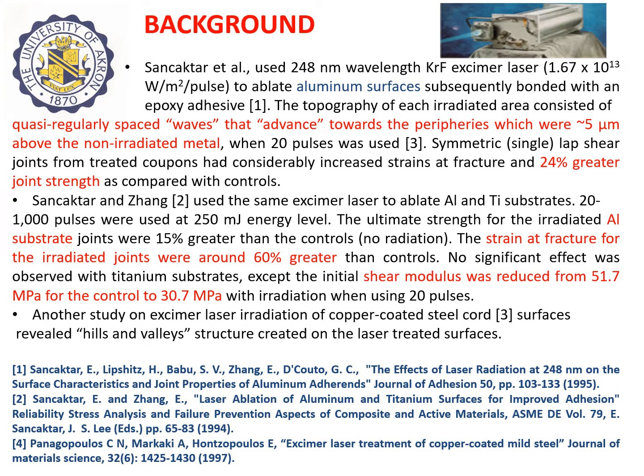We also performed another project where we again looked at aluminum and titanium surfaces. We used pulse numbers varying between 20 and 1,000 pulses applied at 250 millijoules energy level. The ultimate strength for the irradiated aluminum substrate joints were 15% greater than the controls, and the strain at fracture for the irradiated joints were about 60% greater. With titanium, no significant effect was observed for the stress and deformation values, perhaps due to the stiffer, harder nature of titanium. But we did observe a reduction in the shear modulus from 51.7 megapascal down to 30.7 megapascal when we used 20 pulses, which indicated a softening behavior.